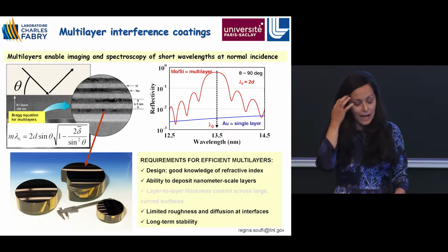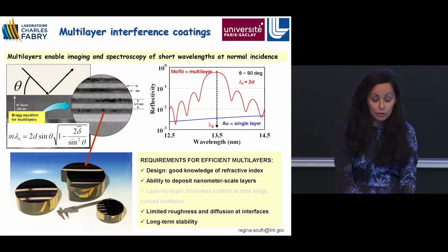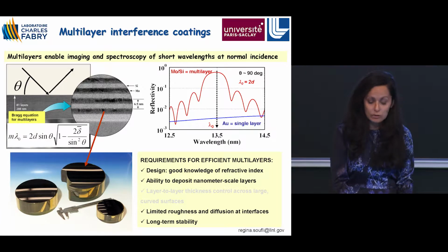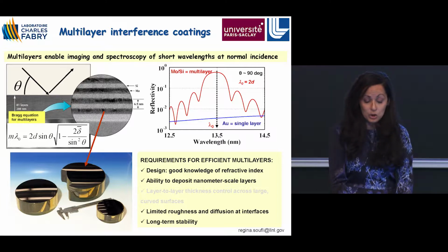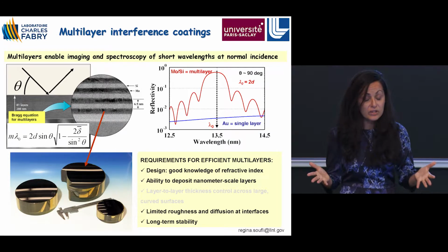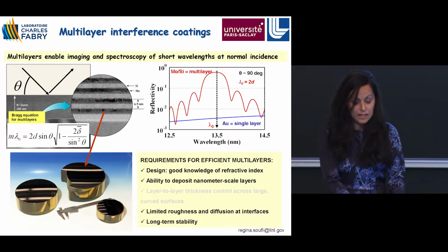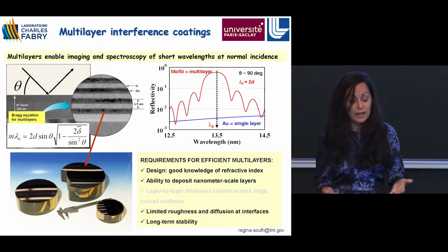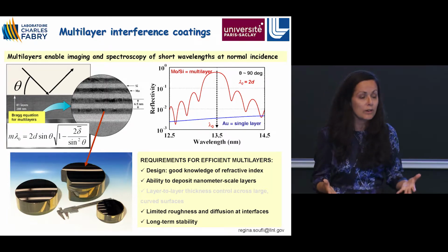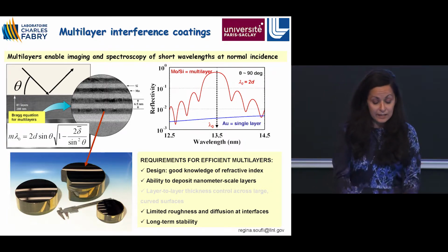First of all, for the design, you need to have a very good knowledge of the refractive index, which you don't, as I'm going to discuss in a moment. You need to have the ability to deposit continuous nanometer scale layers. You need to have layer-to-layer thickness control across large curved surfaces in order to make large mirrors, for example, for NASA and photolithography. You need to have sharp and smooth interfaces. And very importantly, these structures need to have long-term stability over months and years.